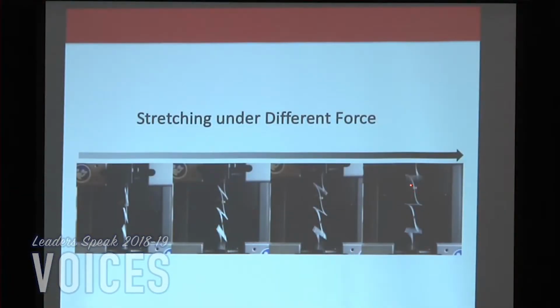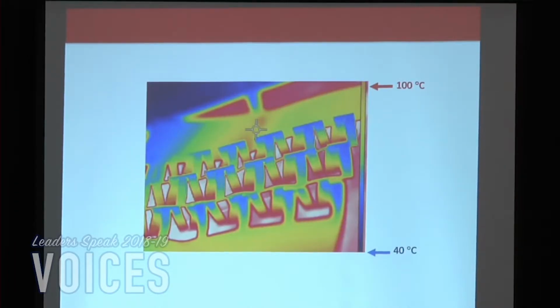And you can see it here stretching. Here's that surface. We stretch it out, and then these little surfaces fold out and become vertical to it. So just by making a structure, paper cutting, so to speak, and applying that same idea to thermoelectrics, we can make a device that might be useful and affordable. And here's the temperature gradient. You can see we're looking at 100 degrees to 40 degrees Celsius.